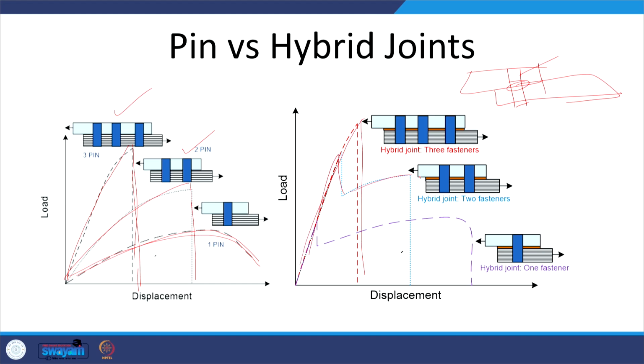Okay. So, when we are using so many mechanical fasteners, the sheet becomes extremely weak and it does not contribute much towards the displacement. But here, when we use 1 or 2 mechanical fasteners, then after failure of the adhesive joint, we get the contribution of the mechanical fasteners in the load displacement curve.